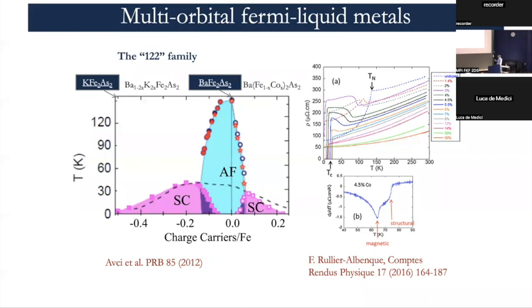What we have, and this can be studied in many families, I like very much the 122 family, which is a family that you can dope in several ways. For instance, electron doping and hole doping. And hole doping brings from 6 electrons towards 5.5 electrons. You can get all the way to the other stoichiometric end members. So you go from barium iron arsenic 2 to potassium iron arsenic 2, where you can do also isovalent substitutions. So you can dope from 6 electrons towards half filling, and we have characterized that when going towards half filling, very important things happen as far as correlations of the electrons are concerned.